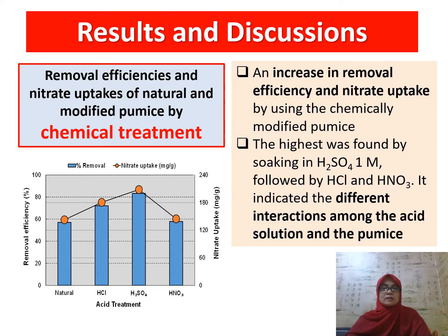This is the result of chemical treatment of modification. These figures show an increase in removal efficiency and nitrate uptake by using the chemically modified pumice. The highest was found by soaking in sulfuric acid, followed by hydrochloric acid and nitric acid. It indicated the different interaction among the acid solution and the pumice.